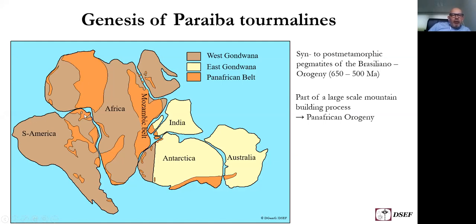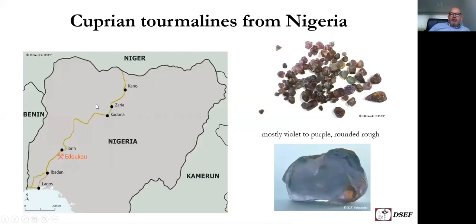When we now jump into Africa, we land in Nigeria, which is located approximately here. It was actually in about 2000 when the first Cuprian tourmalines from Nigeria appeared in the trade. They were found at the Edeukou mine near Ilorin, some 150 to 200 kilometers east of the border to Benin, and some 20 kilometers south of the city of Ilorin. Most of these stones that appeared in the trade were violet to purple. They were rounded, rough, and water-worn, so they came from a secondary deposit, not crystals like we saw in Brazil. And this is quite a large stone of about 200 carats, if I remember correctly.